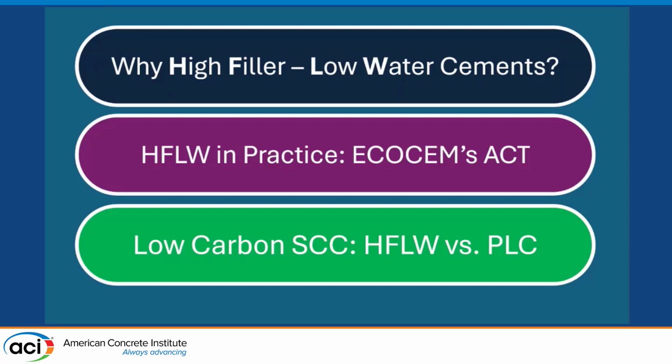We've done some recent ASTM C1157 testing, and it passes a low heat of hydration type for C1157. So that'll give you the calories. We can also comment on the setting times. The setting time is fine. You just have to be real careful with admixtures. Sure, that's my next question. Well, you go ahead with your question. I just want to make additional comments.